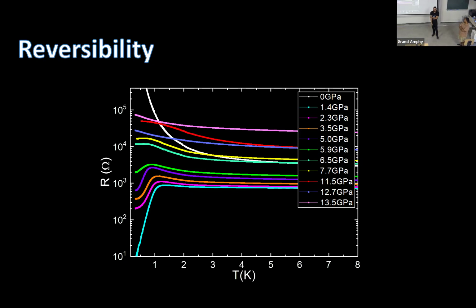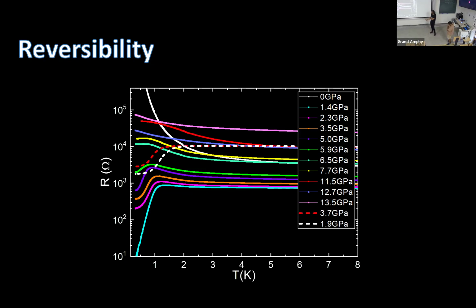So yeah, this is a concern that we had, because pressure in many materials does cause this topological change. This is the same graph that we saw before. In this measurement, we were able to go down, and we can see that it goes back to this M1 phase when we see that decrease in the resistance. It's much different in the value, but the TC is pretty much the same. It's harder to measure because we lost contact along the way. So this is the 2-contact measurement compared to this 4-contact, and it's maybe not fully reversible, but the fact that we go back to some superconductivity, to some drop, indicates that we don't think it's.